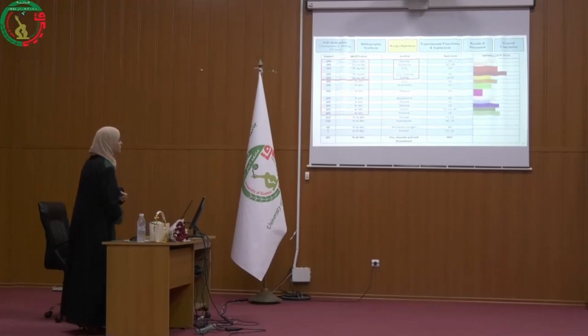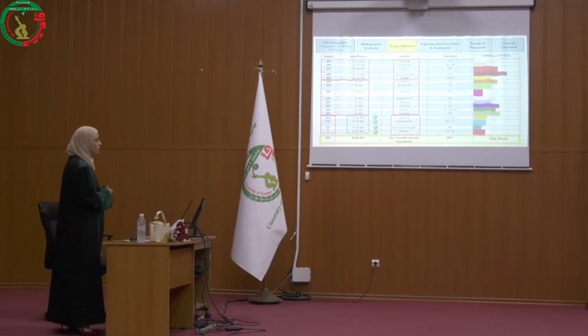While the modification of screen-printed electrodes with bimetallic materials is common, the use of platinum and nickel together is rare, especially for our target analytes. Most studies focus on using platinum or nickel individually, and even Pt-Ni systems found in literature are not for our target analytes, nor do they use screen-printed electrodes. This takes us to the second novelty of our work, which is the first-ever screen-printed electrode modified with platinum and nickel nanoparticles for the simultaneous detection of zinc, ascorbic acid, and paracetamol.